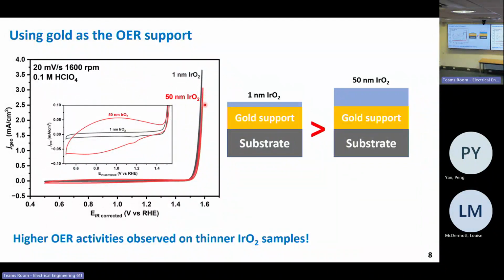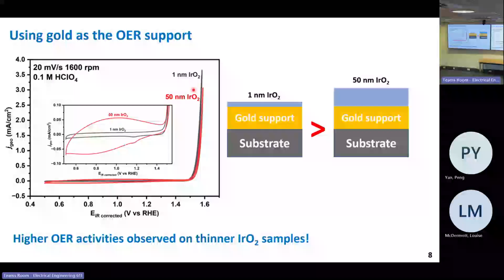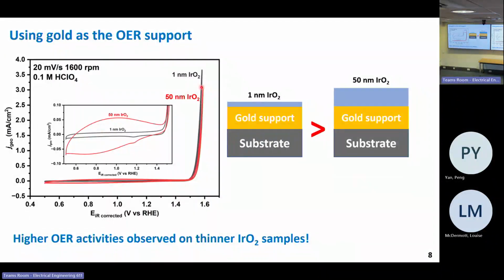So we sputtered crystalline iridium oxide of 1 nanometer thickness and 50 nanometers on top of a gold support. Gold is the most commonly used backing electrode to study water oxidation. And surprisingly... why? Because gold is quite stable under water oxidation. Well, it's relatively stable, and it's still conductive.